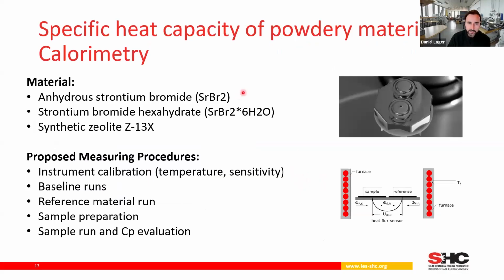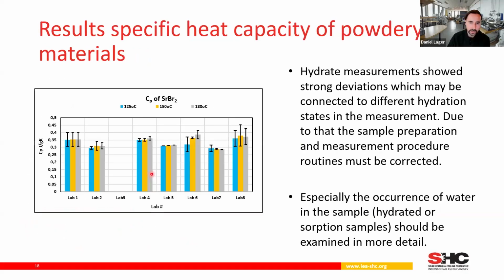For specific heat capacity of powdery materials, we also looked at 3 different materials: strontium bromide, a hexahydrate, and a zeolite 13X. And here we defined the procedures for the calibration and for the systematic baseline runs. Baseline runs means the systematic deviation of the system itself. Then measurements with reference materials. We harmonized the sample preparation. And then we also did a harmonization of the specific heat capacity evaluation.